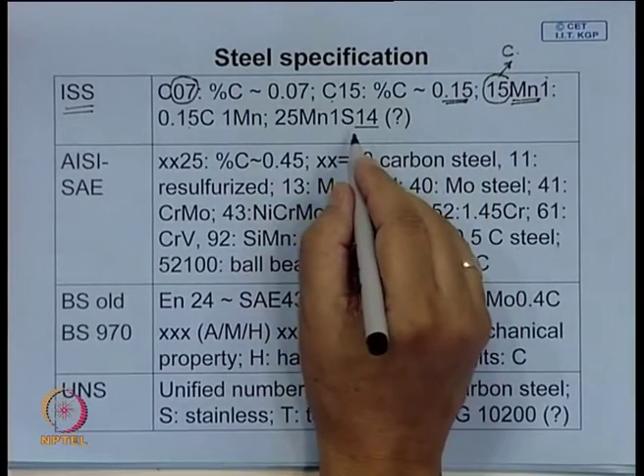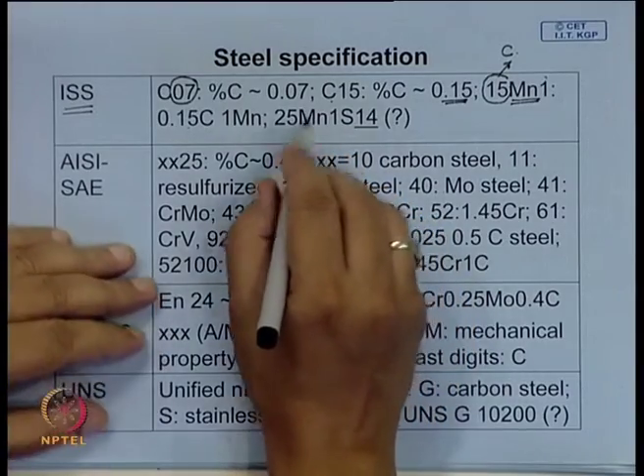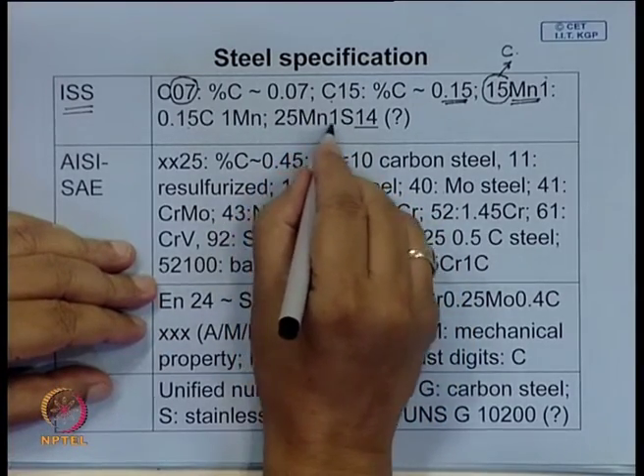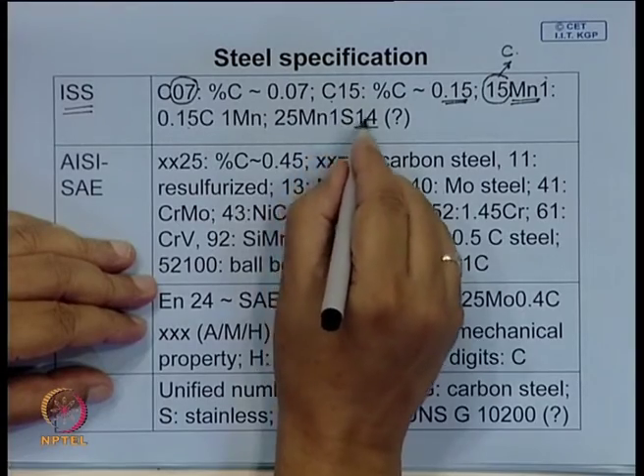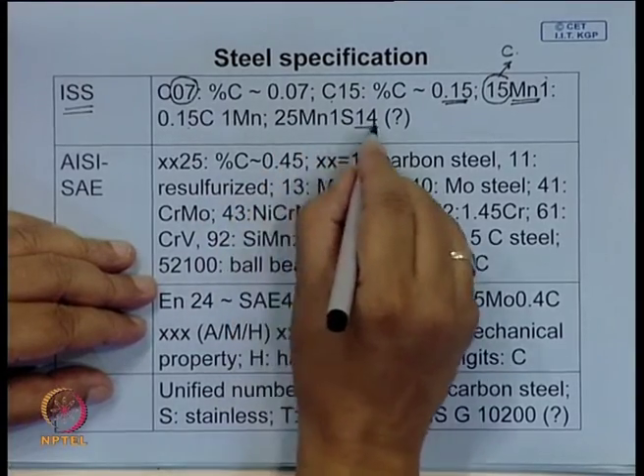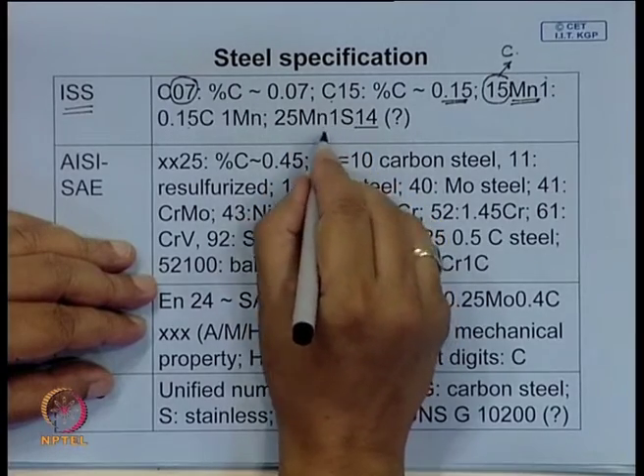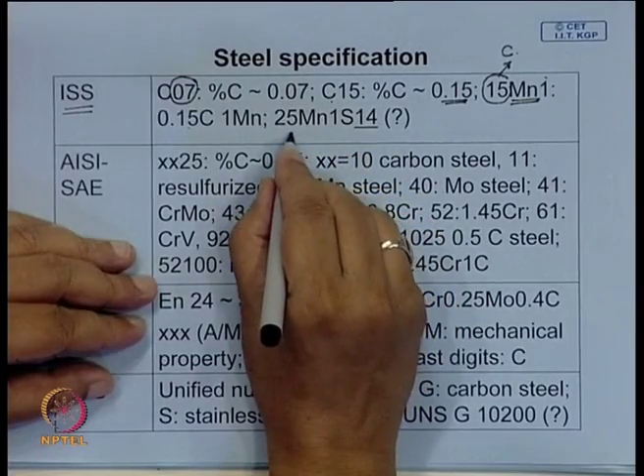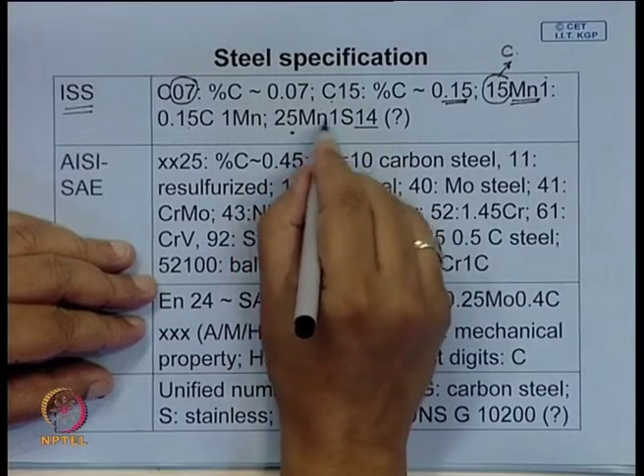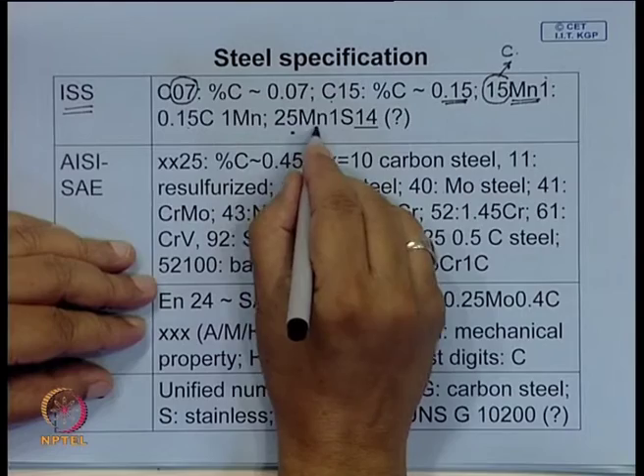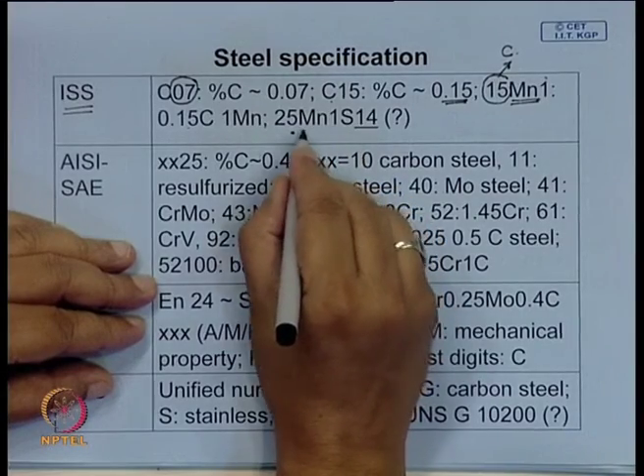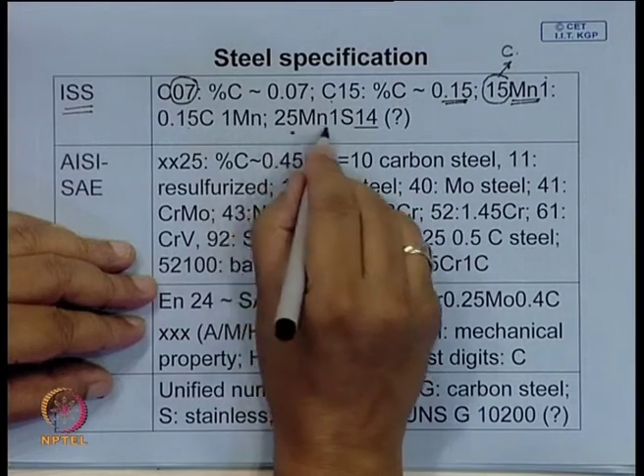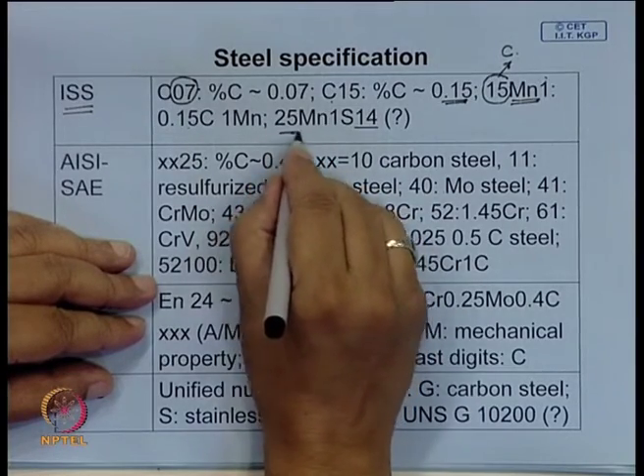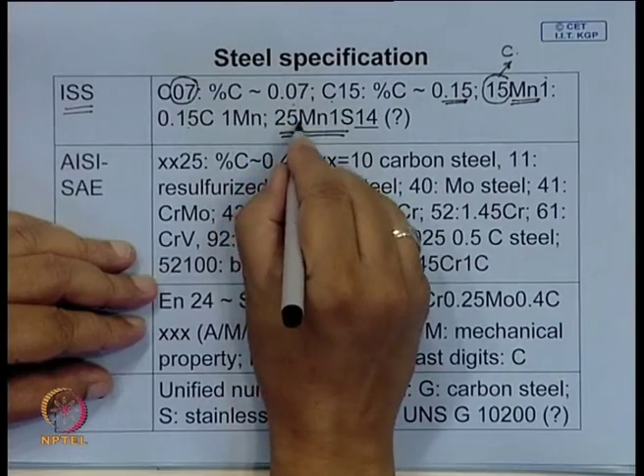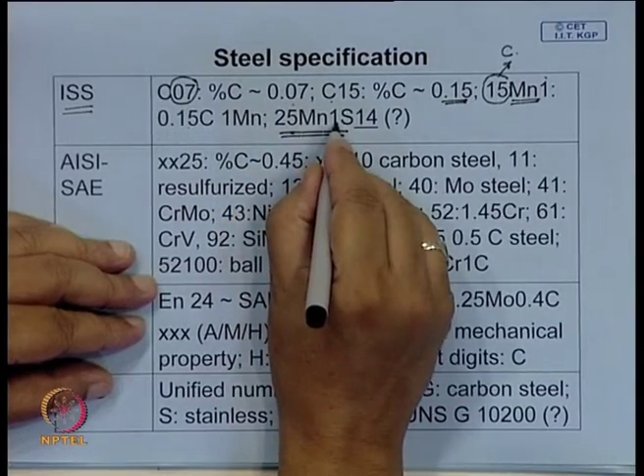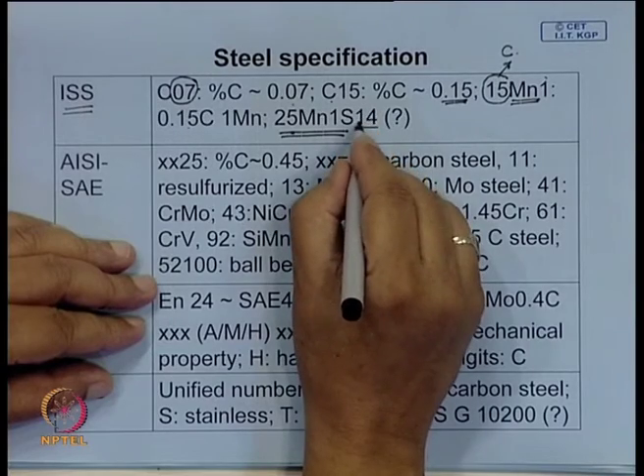Sometimes you have more elements. There are certain grades where normally sulfur is undesirable, but there are certain grades where you add sulfur. This is particularly where you need very good machinability. There you need a little bit of inclusions made of manganese sulphide, which improves the machinability of steel. So, this is one such steel. Here 0.25 is the carbon content, manganese is 1, and sulphur is 0.14.